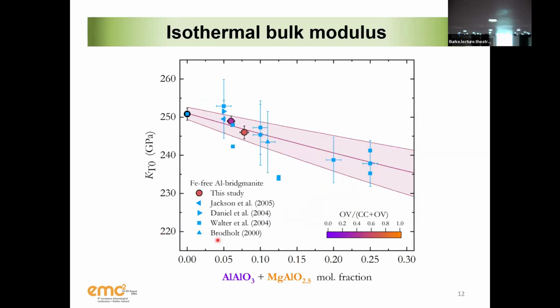That's the first observation. The second observation is that the large difference that we're seeing in the bulk modulus, so in the compression of these two materials, is probably not there. There is some hint that your oxygen vacancy mechanism is a little more compressible than the coupled substitution, but the difference is not as large as other studies were saying. At least that's what we think. All the other studies were done, of course, on powder, and they were done quite a few years ago. So it's not that they are wrong. They did the best that they could with the technique of that time. It can be completely wrong, and in 20 years somebody will tell you it's not true, but this is what we could do with the technique of today.